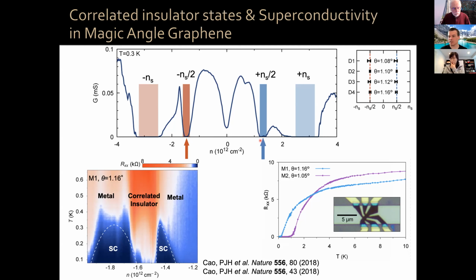Yeah, your system is an insulator, even though your Fermi energy is in the middle of a band. Okay, and it should be a good metal. That occurs only for a relatively small range of angles around that 1.1, roughly between 1 and 1.2, maybe a little bit larger. And to the surprise of, this was already a big surprise, but an even bigger surprise was